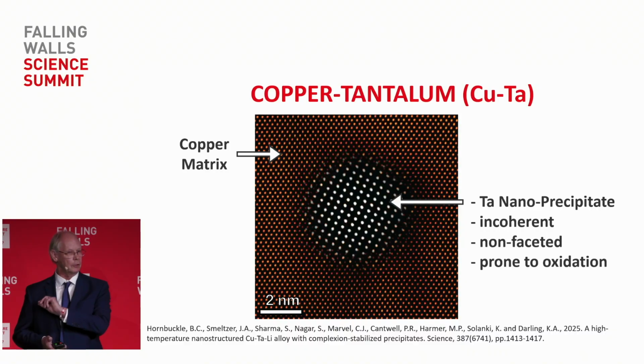and these really tiny precipitates and nanoclusters, only a few nanometers of tantalum. And it does a pretty good job at pinning the structure, stabilizing it, and giving you reasonable properties. It's a very good start in the alloy development. But there is some oxidation of the tantalum, and there's some growth of the particles, so it's not ideal.